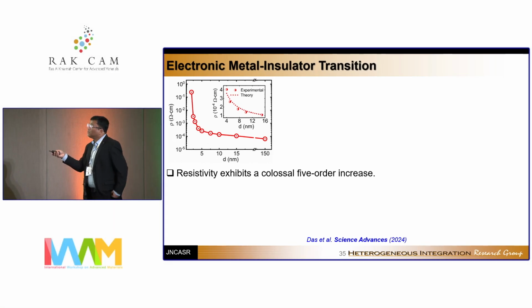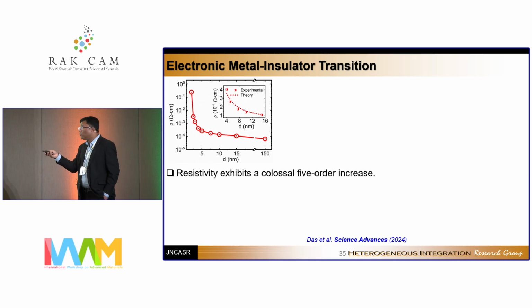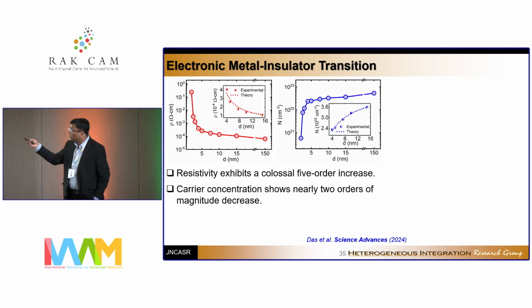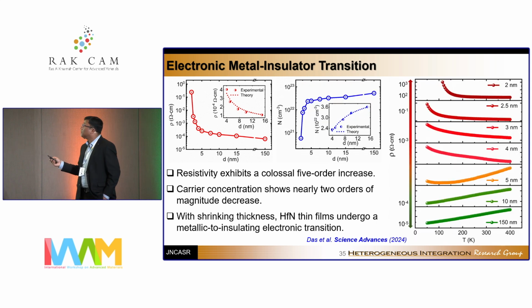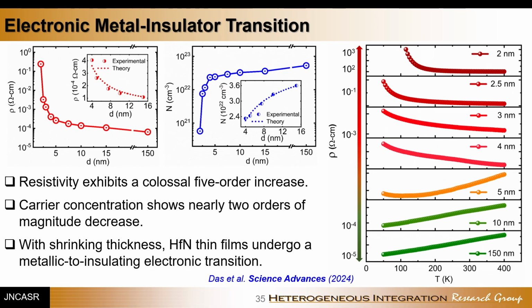So as you reduce the thickness from a large 150 nanometer to a small 2 to 3 nanometer, you see the resistivity increasing by 3 to 4 orders of magnitude, carrier concentration decreasing by 2 to 3 orders of magnitude, and the temperature dependence of the resistivity also satisfies what normally you would expect, namely that in a metal, the resistivity should increase with temperature, whereas for a semiconductor or an insulator, the resistivity should decrease with temperature.